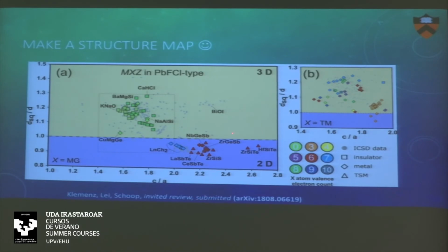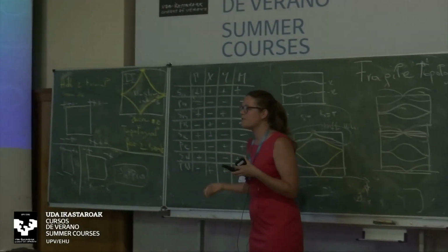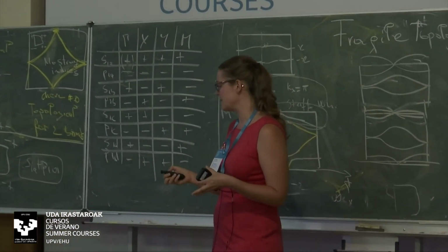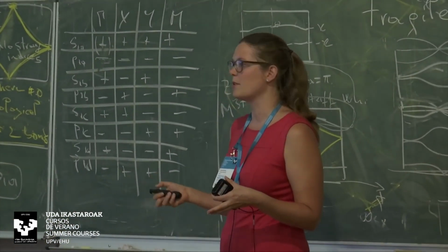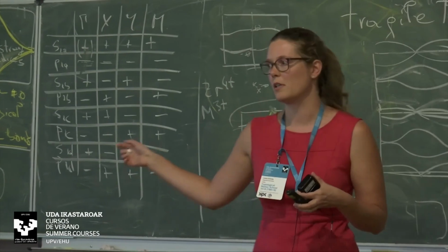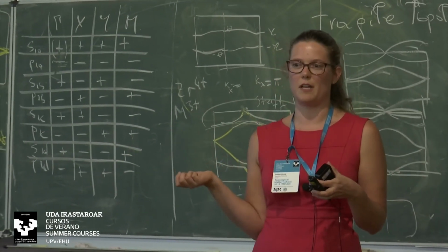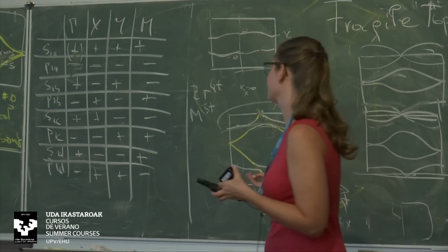understand why. Because, okay, in zirconium silicon sulfide, we had zirconium 4+, and we said the 4+ is a good oxidation state to stabilize the square net with the d electrons. Then, if the atom is 3+, we basically have 0, like we have only these 2 examples here of lanthanum and cerium antimony telluride, and all the other ones distort. So 3+ is not that good of an M cation to stabilize the structure.